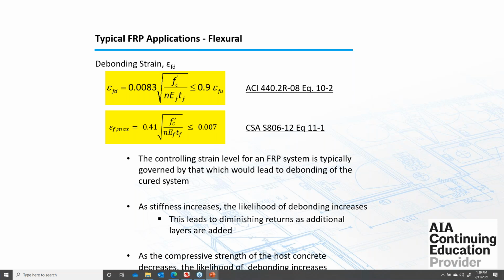But you can see here, it really depends on the strength of the concrete, f'c, the compressive strength of the concrete. And then on the bottom, you've got n, the number of layers of material, then the stiffness times the thickness of that material. So as we increase the number of layers, this allowable strain starts to converge on 0. Generally, with your standard 600 grams per square meter, the 18 ounce per square yard material, around 3 or 4 layers you start to get to that 0 strain. So adding 5, 6, 7 layers is going to add a very, very small amount of additional capacity.